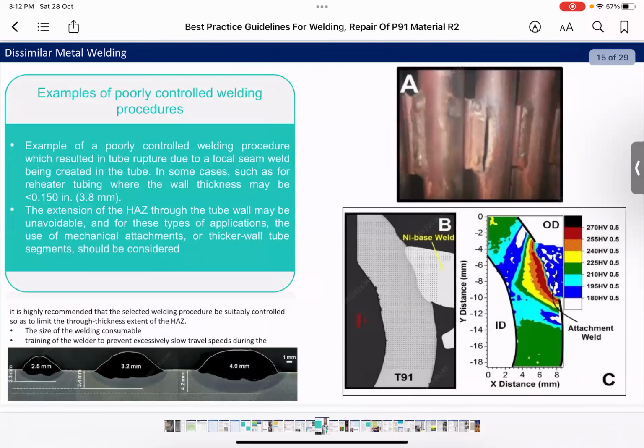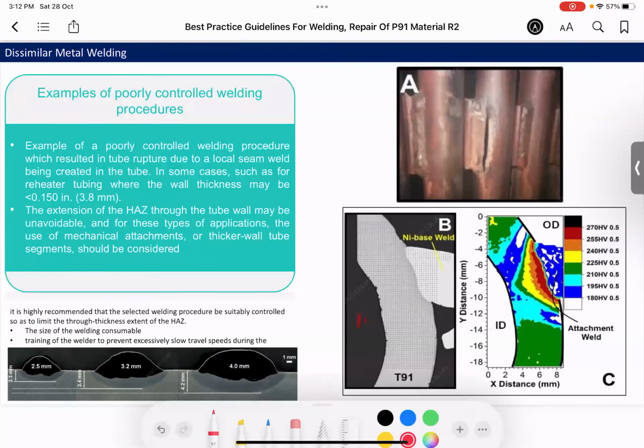This is an example of poorly controlled welding during dissimilar welding. We see in this colored photo, the depth of the heat affected zone is almost 70 to 80% of the wall thickness of the tube. So this created a problem, and the crack initiated from there and resulted in a rupture in the joint. So this is due to high heat input during welding.